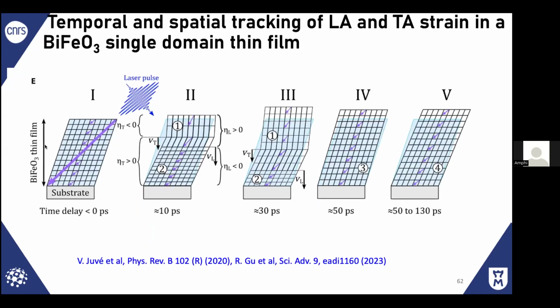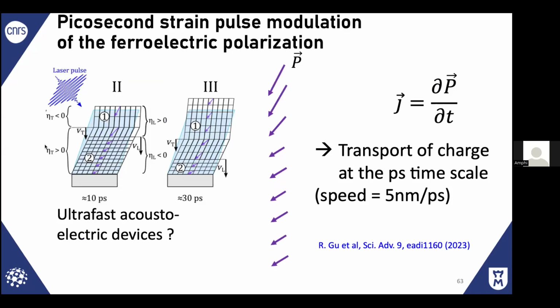So basically, this is a thin film, ferroelectric film, and we have resolved not only as a function of time, but also as a function of space, which is very important, how the unit cell evolves in such a thin film. And from the physics point of view, what is interesting is that if you consider a strain pulse, a phonon wave packet that propagates, there are two components, longitudinal and shear, and this induces a modification of the ferroelectric polarization, which is related to the current. Probably this has not been measured, but we are combining such experiments with THz experiments just to detect that transient of the polarization.